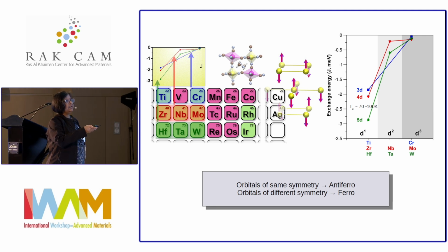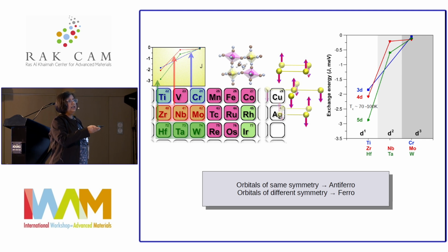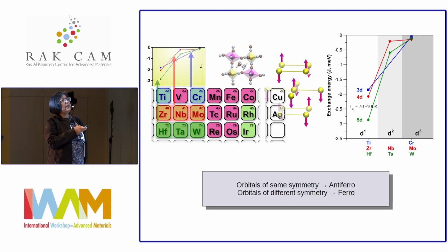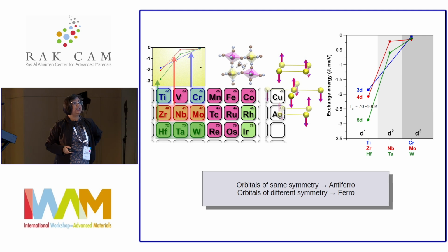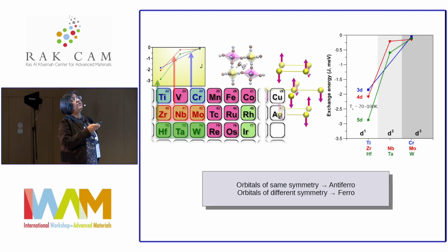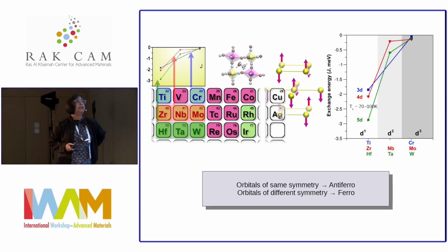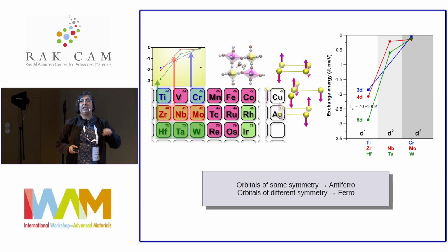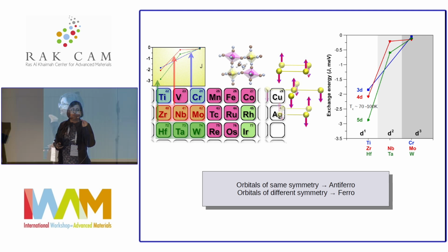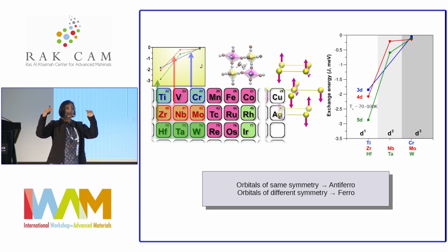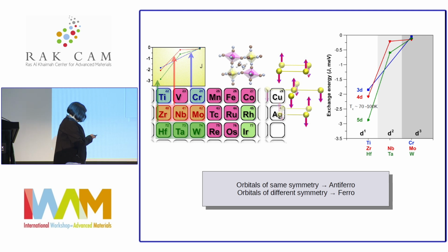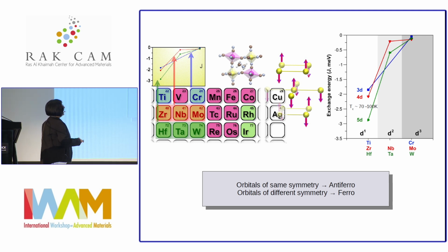And these are the materials which are with this D1 configuration. These are with D2, and these are with D3, as is shown here. And what we find is that the D1 configuration gives rise to the largest value of the antiferromagnetic exchange interaction, while for D2 and D3, the values are much smaller. So why does that happen? D1 means you have one of the orbitals occupied by one electron, and you have the orbital of the same symmetry that overlaps through a super exchange to give rise to a magnetic interaction, which, according to the Goodenough rule, should be an antiferromagnet.